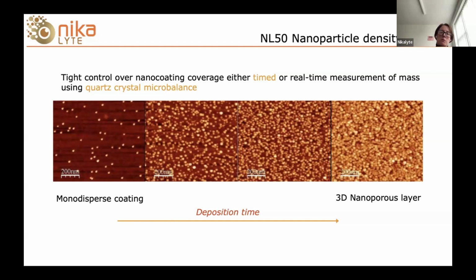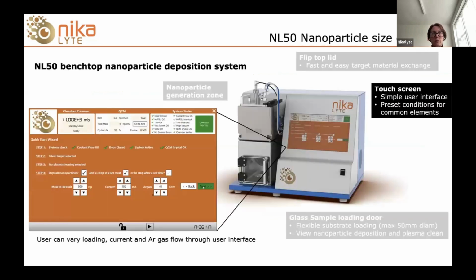And not only that, we can reproduce this time and time again because we're measuring live as it's depositing. If there's any fluctuations in the deposition rate, we will see that as the process is being run, and we can adjust for it. And you can control the loading. You can actually put in a particular loading that you want to achieve into the program, and the machine will generate that for you. So that's really important that control is present.